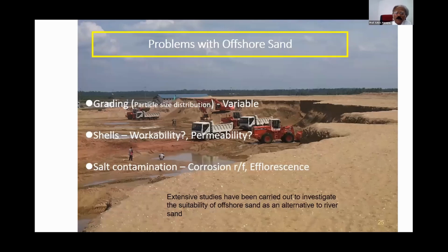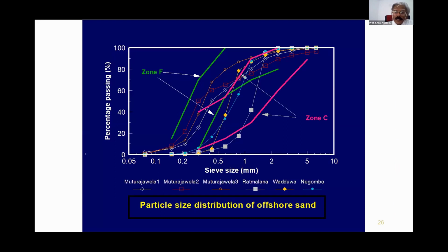So what are the problems with offshore sand? The grading, that is the particle size distribution, can vary depending on where you dredge the sand. Then the shells. Will shell fragments in offshore sand affect the workability or the durability of concrete that you produce from the offshore sand? And the biggest problem is the contamination, the chlorides. Now that can promote the corrosion of reinforcement in reinforced concrete, and also you can get white patches on the surface of concrete if you use offshore sand with chlorides. Extensive studies have been carried out to investigate the suitability of offshore sand as an alternative to river sand, and these are the results.